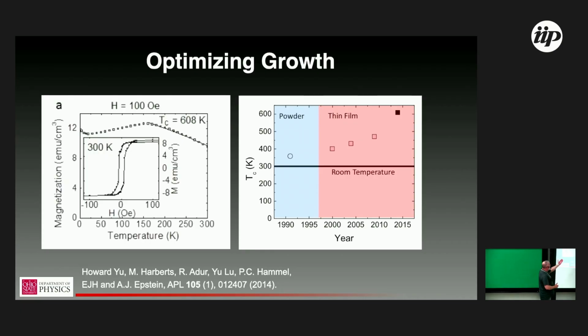But if we take what I would consider a more physics perspective, as opposed to a phenomenological perspective, on what TC means, just take that as an energy scale associated with the magnetism in the system. Then you can fit that high temperature region to a Bloch law and say, okay, well, where would I predict that to hit the axis? And you get something of about 600 Kelvin.